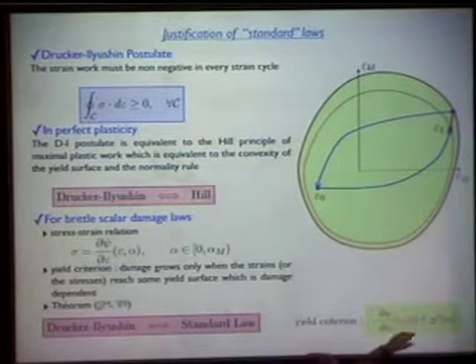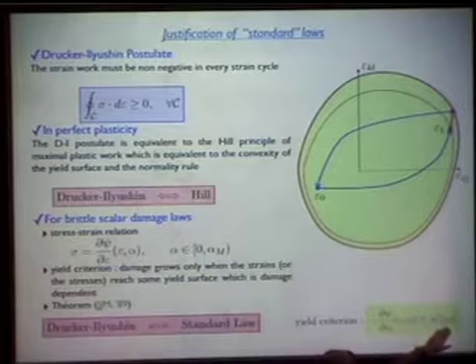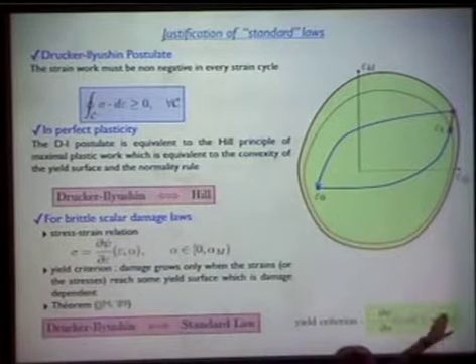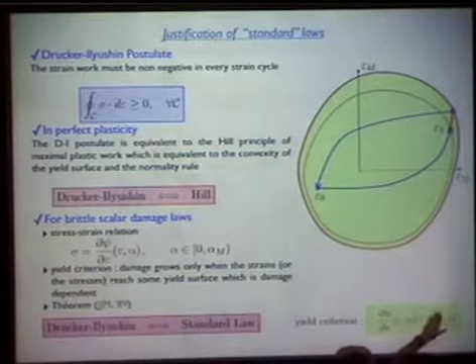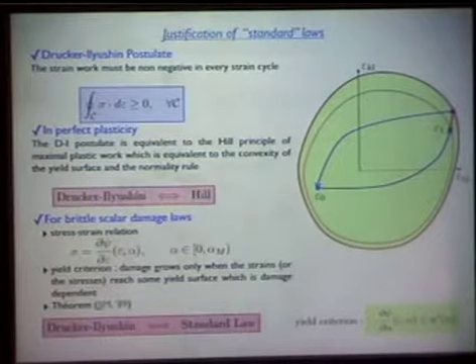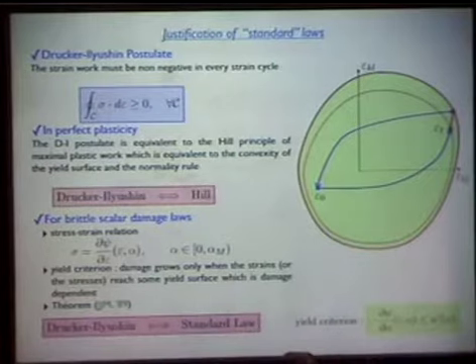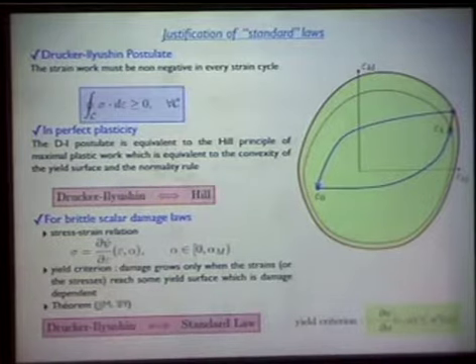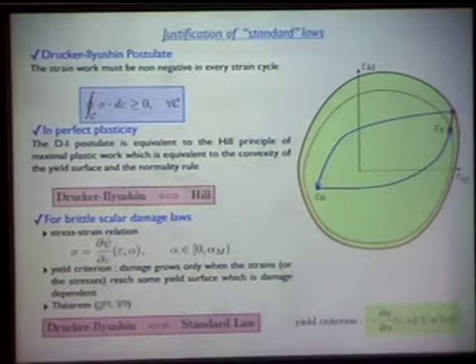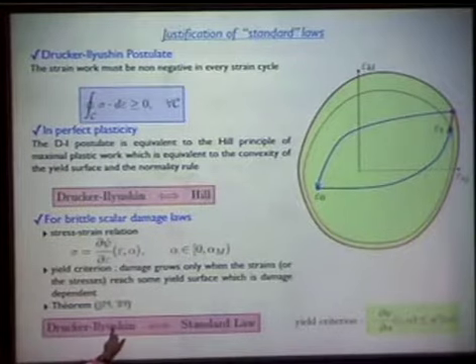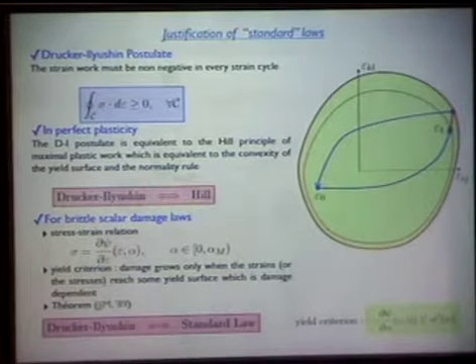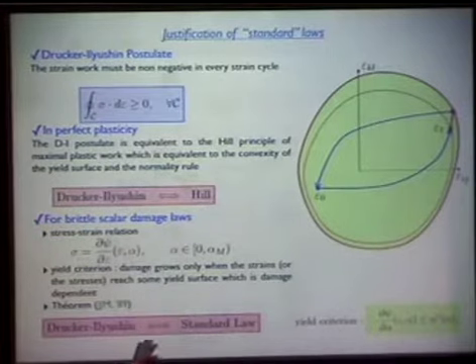This is like a Griffith criterion. By changing the variable alpha you can consider this quantity as a constant. The key point is that the shape of the elastic domain is given by this derivative, and this is essential to obtain a variational formulation of the damage problem. This is a physical principle justifying this type of model, and the proof is not difficult.